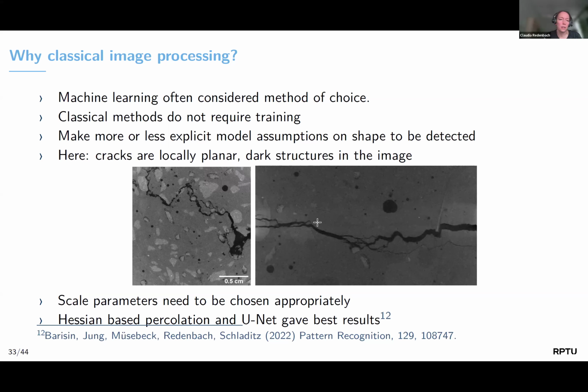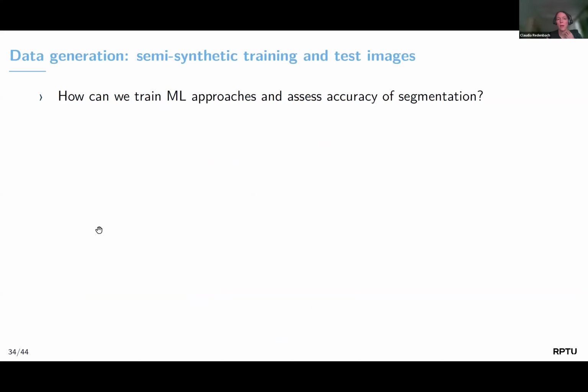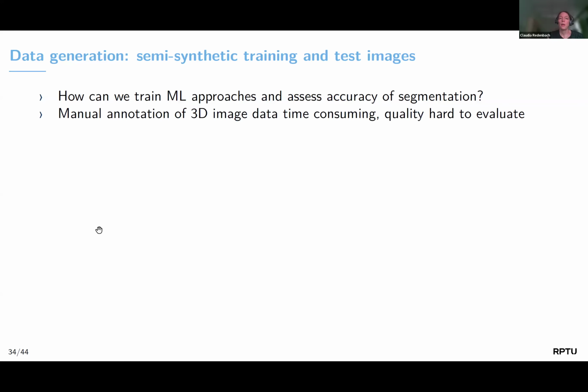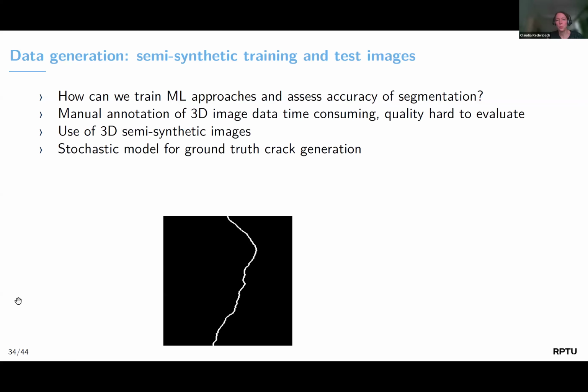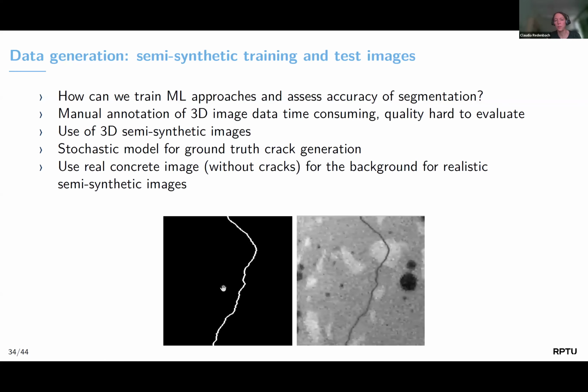In our comparison study that we refer to here, we found that the Hessian-based percolation was the best classical method, and among the machine learning methods, UNet gave the best results. Now we could ask, how is it possible to actually say that one method is better than the other? We need to be able to assess the accuracy. And also for the machine learning methods, we need some training data, so we need annotations. Nowadays, manual annotation is still often done, but the quality of the annotation is hard to evaluate and it's very time-consuming. So what we did is we used the stochastic model for a ground truth crack generation. Then we superimposed such a synthetic crack here with a real image of concrete without a crack.